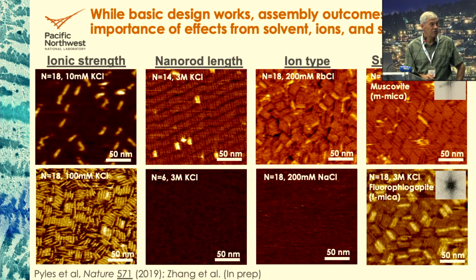Now here's perhaps the most remarkable outcome. This is what we get on muscovite, which is one type of mica. You get the smectic phase, or nematic phase if it's not quite as high a concentration of salt. Fluorophlogopite is another type of mica that has exactly the same surface lattice. That lattice I showed you in an early slide, it's the same in both cases, but we can never get out of the high density disordered phase. This phase will never appear, no matter how high the concentration of protein or salt.